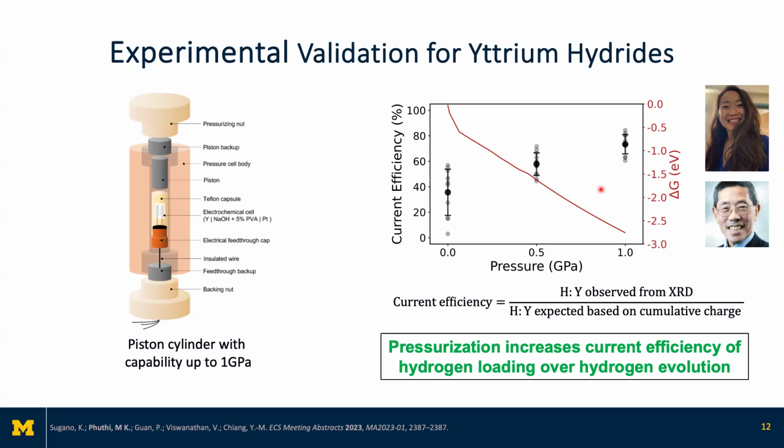YH3 is becoming more stable because it has this lower delta G, but this delta G is also related to the kinetics in that it gives you the thermodynamic driving force. So how much do you really want to form YH3 over YH2? That is correlated through things like the Bell-Evans-Polanyi relationship, if you're familiar with it, which is related to the kinetics.